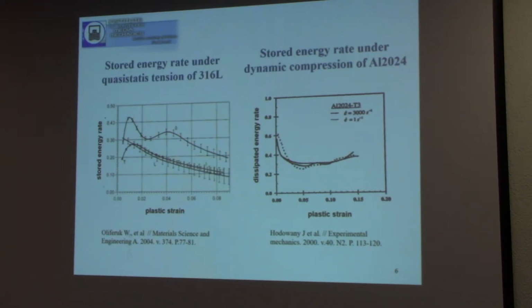And if we go to new experimental investigations, I have to mention the team of Professor Oliferuk. She made very interesting experiments with control samples, and measured the rate of stored energy under plastic deformation of steel. And we can see that the rate of stored energy can increase up to 46% in the beginning of the plastic deformation process. Here in our work, it's dynamic loading, and we can also see a dissipated part. It's quite small for some materials.